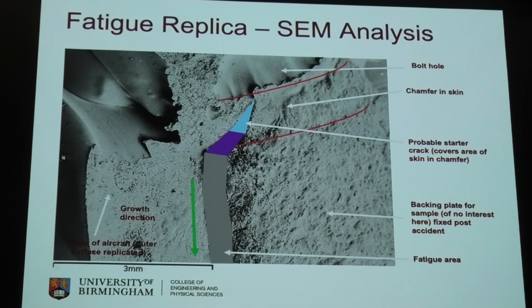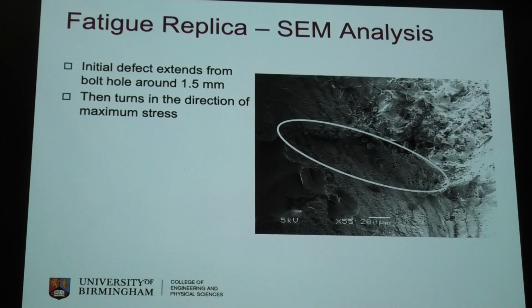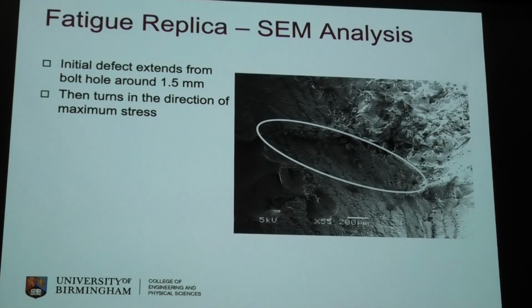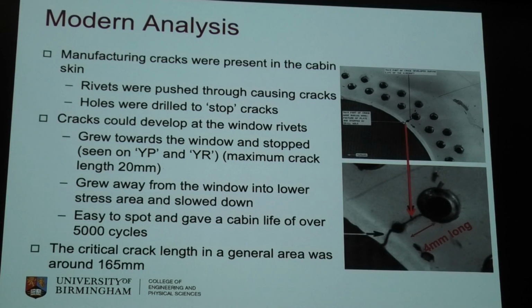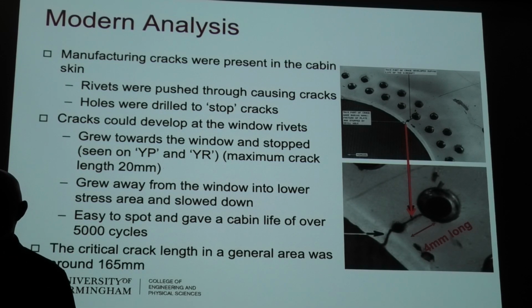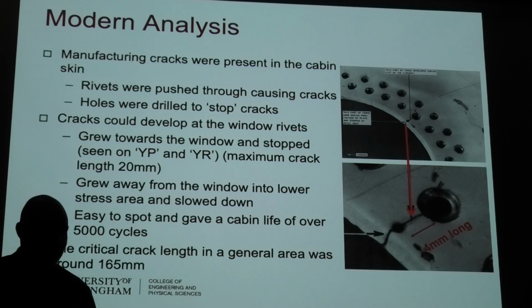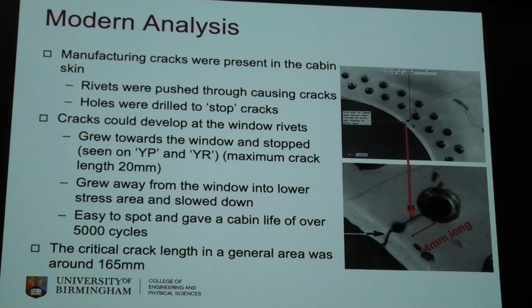Probably the starter crack covers an area of skin in the chamfer, then it changed direction, to the direction of maximum stress. As I said, about 1.5 millimetres long before it changed direction, so that's probably the initial starter crack. And we knew that these defects were present because we've seen them before, so we knew that a lot of rivets would have cracks under them. And now you've got a race to the finish. The longest crack in the highest stressed area will bring your airframe down first, which is why there was such a scatter. And the ones with the longest times in service were always likely to be the planes that came out of the sky first.